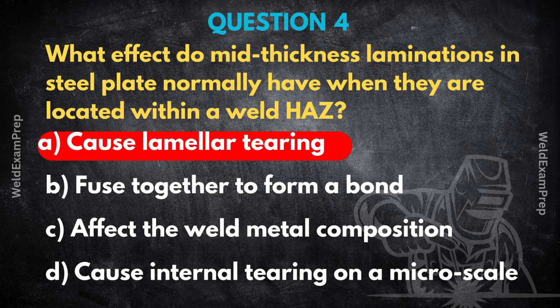So you've got this unstoppable vice grip, the shrinkage stress, pulling apart a fragile, layered piece of metal, the lamination, in the most sensitive area, the heat-affected zone. And lamellar tearing is the inevitable result. The weak plane of that lamination just rips open under the shrinkage stress. It's a severe, through-thickness crack that you'll often see running parallel to the fusion boundary.